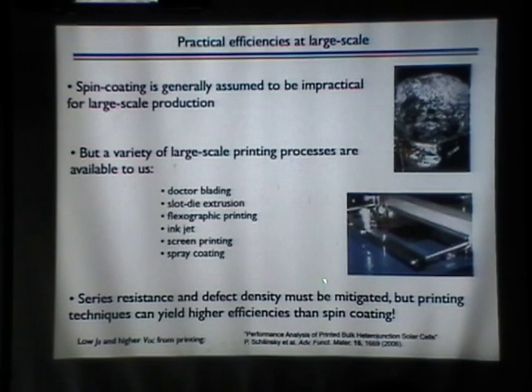Let's see. So one issue when you go from small area to large area is you want to mitigate defects in the material. That was a problem for cadmium telluride for a long time. They could make very efficient small devices, but when they went to larger area, the defect density was too high and the device performance suffered. Now they're getting better at making those large area devices, and we hope to follow the same path with organics.